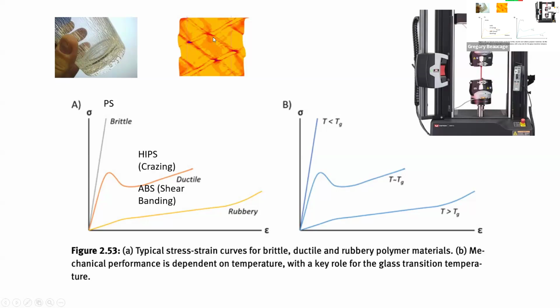Anyway, whenever you have this kind of mechanism, so you pull on it, this is the stress versus the strain. This is the force divided by the area, this is the change in length divided by the initial length. So basically polystyrene looks like that and it breaks. Just straight up bang, that's it, like glass. Then if you start having shear banding, so you add the rubber, adding butadiene to make HIPS increases the shear banding. So you get a yield point. So it starts to shear band. When it's shear banding, the force actually drops, then it plateaus out. So all along this way, it's not shear banding, it's crazing. So all along this way, it's crazing, and finally it reaches too big of a size.